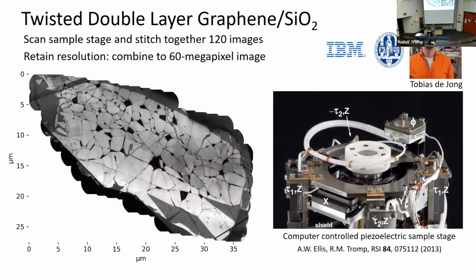So let's look at graphene a little more. This is a set of experiments done by Tobias de Jong at Leiden University, who will receive his PhD in about 2 weeks. And he looked at a piece of graphene that was transferred using Scotch tape on a silicon oxide sample, right? And so this is an image. It's about 35 microns by 25 microns. And so these are 120 images that are acquired. And you can see sort of the shadows of these images